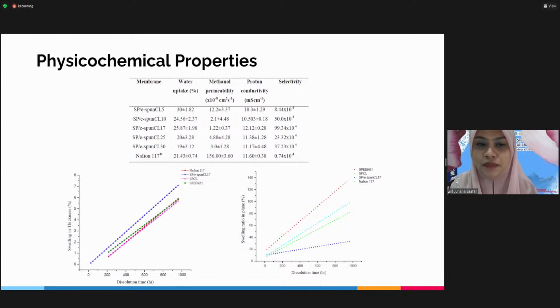As you can see, the best membrane has been selected here based on the highest proton conductivity, the lowest methanol permeability, and moderate water uptake. It shows the highest swelling in thickness and the lowest in plane. This is a really desirable property for a PEM or proton exchange membrane, where this will provide a more intact connection between the membrane and the electrode during the DMFC operation, and consequently can enhance the performance.